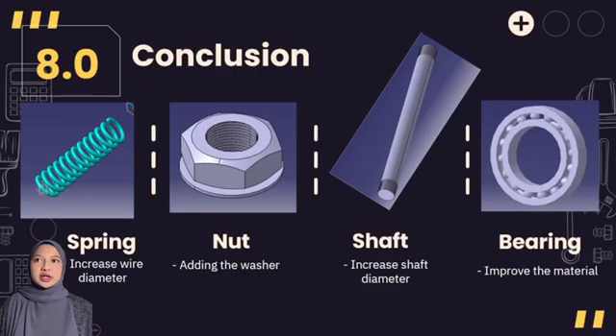So the conclusion for this project, we designed and did the drawing part for the seesaw. The objective of the project has been successfully achieved, and improvement has been done for every component part that we had chosen, which are springs, nut, shaft, and bearings. With proper and suitable analysis using calculation, the design for the seesaw has been improved. To improve the springs, the wire diameter of the spring has been increased. The coil was tightened, thus reducing the spring index, and the spring has become stronger. We also redesigned the screw and fastener by adding the washer and the nuts to make sure the nuts have less bearing stress. The improvement for the shaft has also been done by modifying the diameter of the shaft due to an increased maximum load.